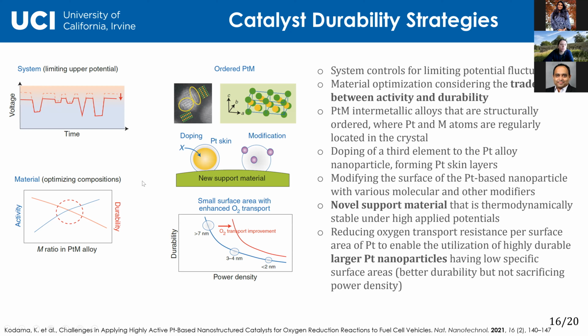Then material solutions: you can play with metal alloys. So for example, platinum-nickel and platinum-cobalt are the most active currently. The higher the M ratio, the better the activity, but the worse the durability. So you can play with that, optimize it, find the optimal one. You can do ordered platinum intermetallics. This has been shown in recent years to be the most promising catalyst for durability, because these ordered structures tend not to dissolve much.